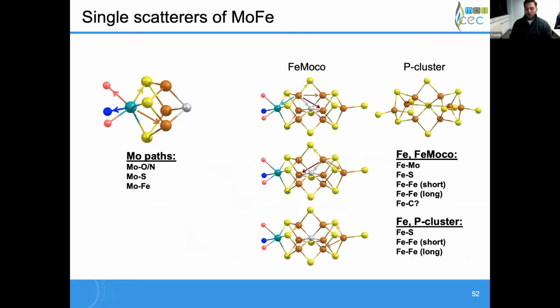And since most of you are familiar with EXAFS, I will just jump into scattering paths right away. Since we have crystal structures of molybdenum nitrogenase, we're very lucky in that respect, where we don't have to guess at the exact coordination numbers and the exact pathways that could be present, because we can already look at the crystal structure to get all of these out.